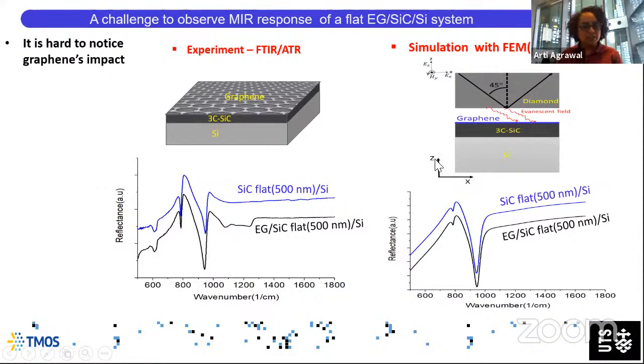We also did this through simulation, using FEM in COMSOL software. And what we find is that for the silicon carbide and the silicon carbide coated with graphene, the features do not change much. So in the planar structure, there doesn't seem to be that much advantage.